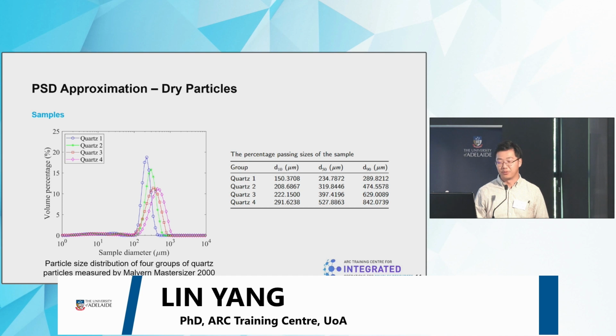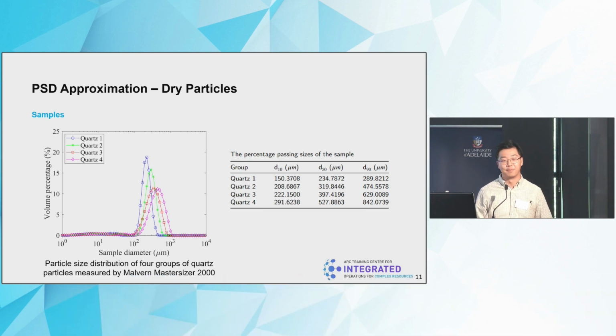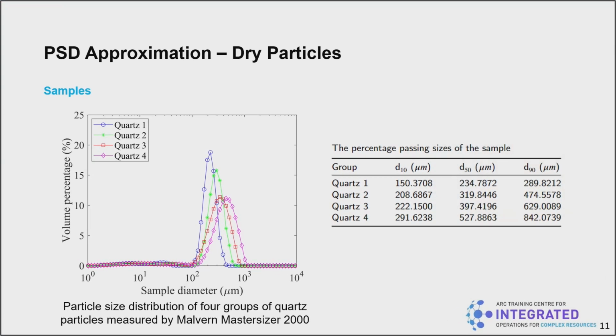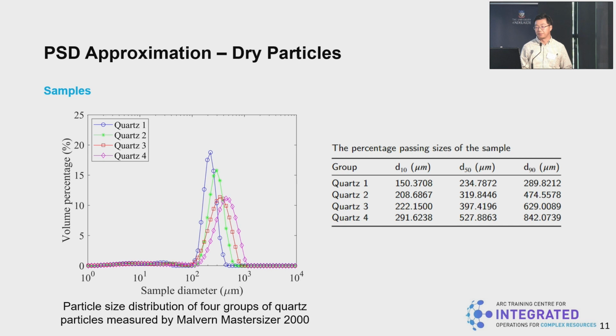As Difan mentioned before, our sensing system can measure the particle size distribution and the mass flow rate of a dry high-intensity particle-laden flow. So here are the test samples that we have for the dry test, which are 4 groups of quartz particles with different but also similar size ranges and particle size distributions. The left-hand side figure shows the particle size distribution, which is measured by a Malvern Mastersizer 2000, an offline laser-based method. So we use this result as the benchmark of our test. And the percentage passing size is also shown on the right-hand side figure.